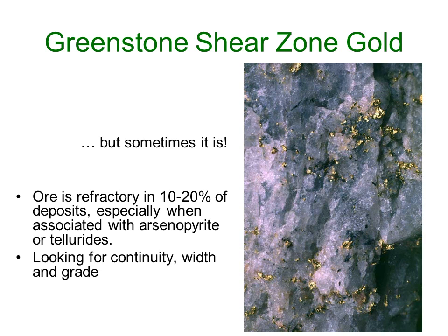You'll also sometimes hear the word refractory applied to gold ores. This usually means that the gold particles are locked up in sulfide grains, and you need to oxidize those sulfide grains in a roaster or autoclave to allow the gold to come into contact with the dissolving cyanide solution. Arsenopyrite is commonly the culprit in a refractory gold ore.